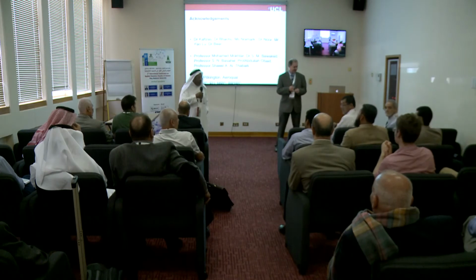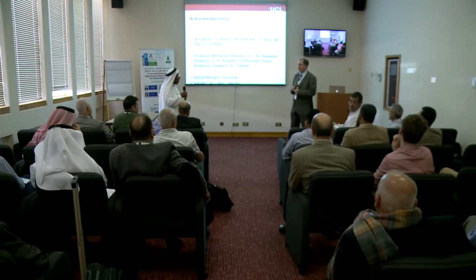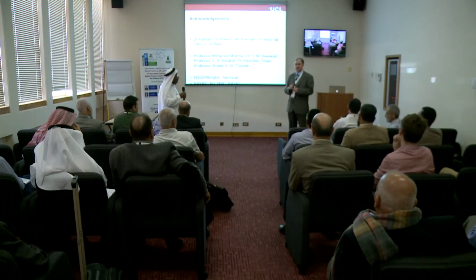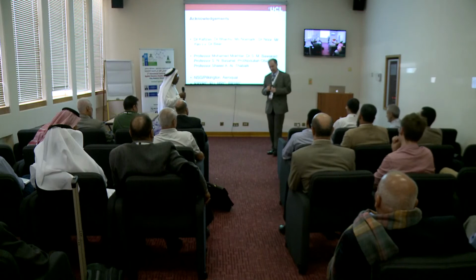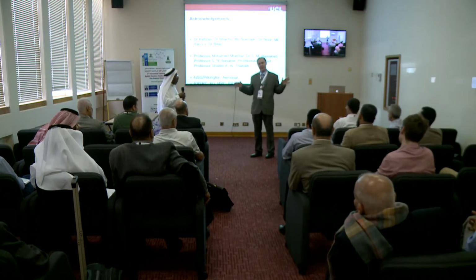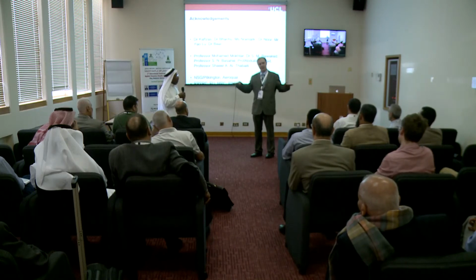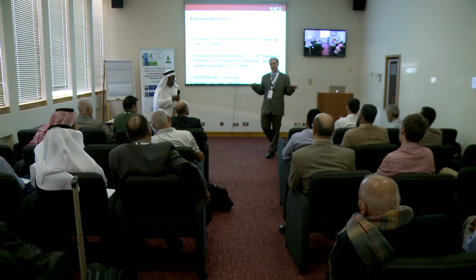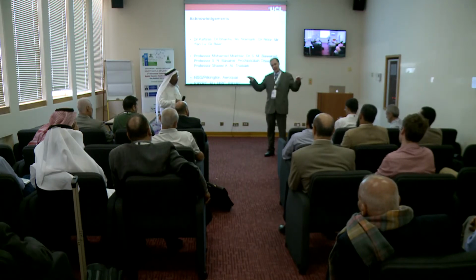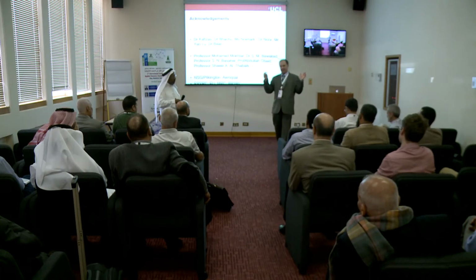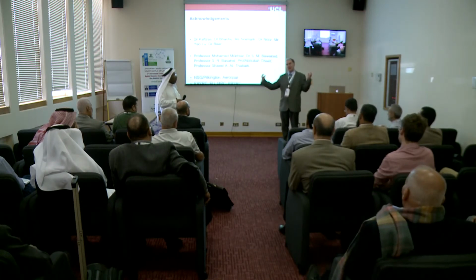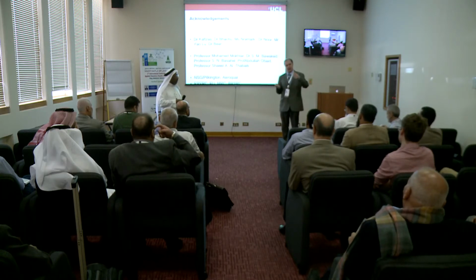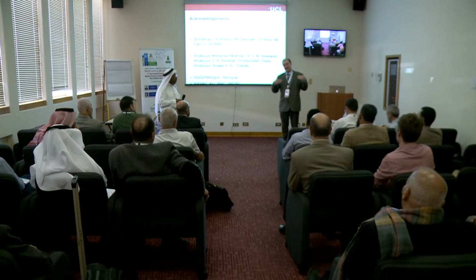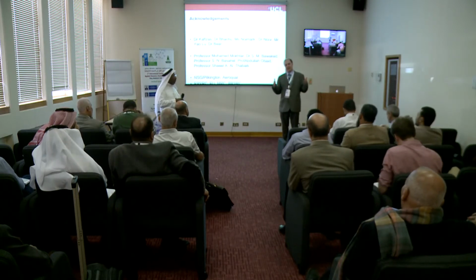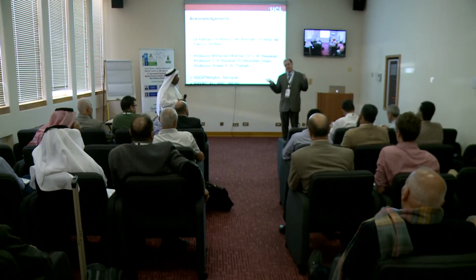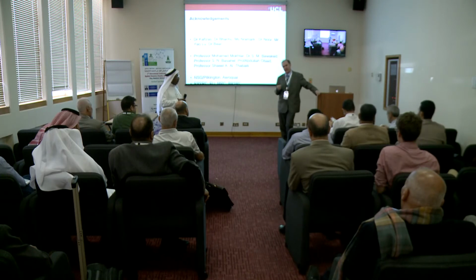Yes, I have a question about the superhydrophobic materials. You mentioned something about the roughness of your surface. How much is the roughness? Roughness is absolutely critical. If you have just a flat planar surface with no roughness, the highest contact angle you can reach is 120 degrees. But when you roughen the surface, you go to extremes. Something which is hydrophilic becomes super hydrophilic, and something which is hydrophobic can become super hydrophobic. Typically, the roughness wants to be on the micron scale. We've used nanometer scale, but it needs to be at least that kind of scale to work.